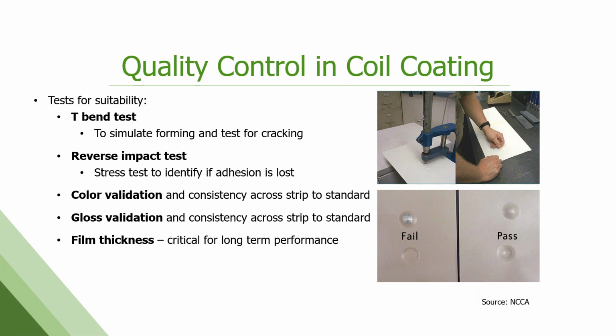Color, huge, right? Color control. We do that numerically and with computers as well as visual comparisons to a controlled standard. Gloss is important, right? That shininess of that surface is critical and is specified for every paint formulation. And then, of course, our film thickness, again, very, very tight, very small thickness of film. We control that to 0.10 mils of thickness. That's the range we have to hit on all of our paint specs. And that film thickness is critical not only for the appearance of the product, but the long-term performance and warrantability of the product as well becomes crucial.